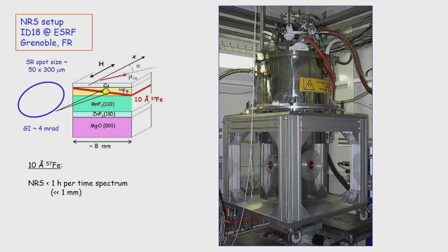And then we went to Grenoble, where we can explore the small size of the synchrotron beam, and we can mount the sample inside of the cryostat. We have a table with a micromotor. That's in this cryostat which moves in front of the beam. That means you can take spectra at different positions of the sample. That means at a different distance from the interface. That is the idea.